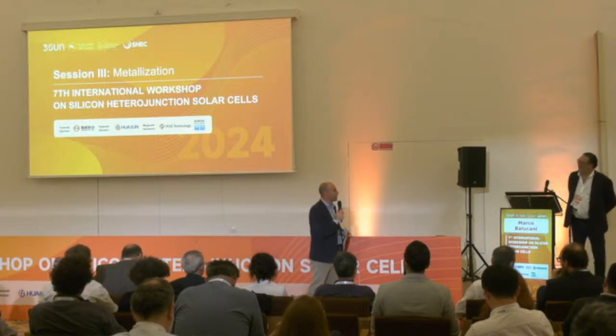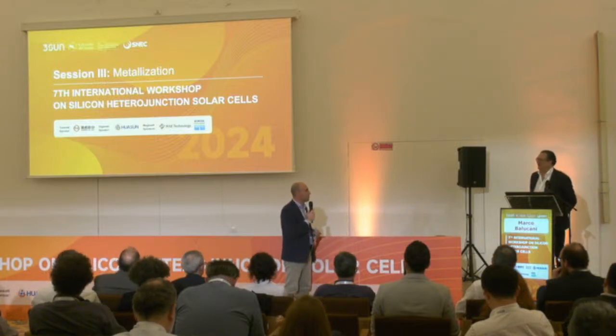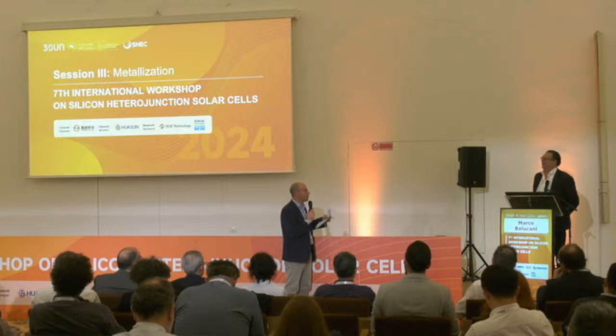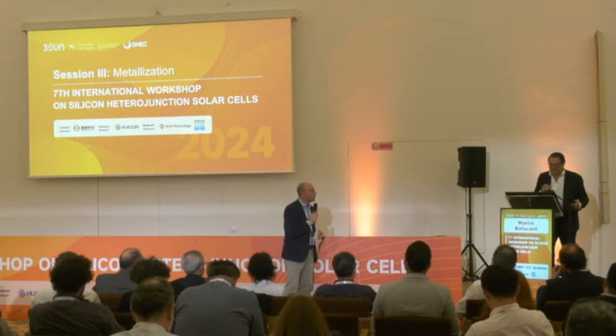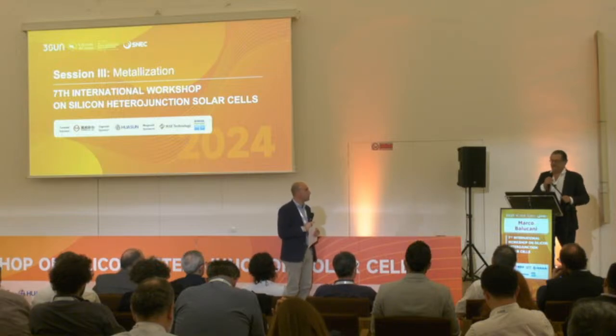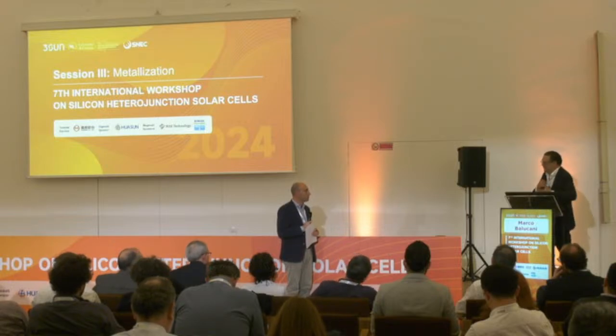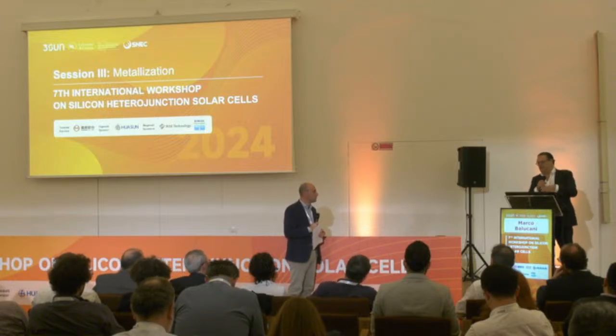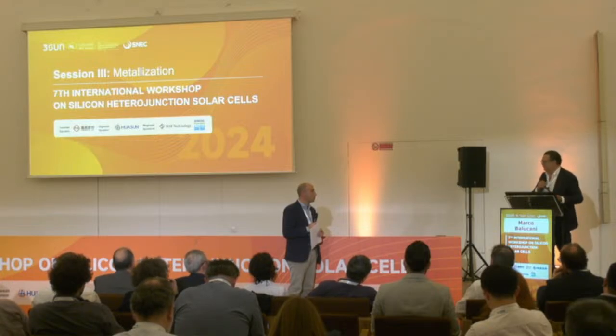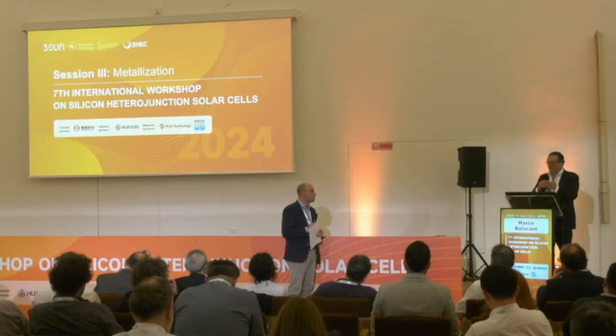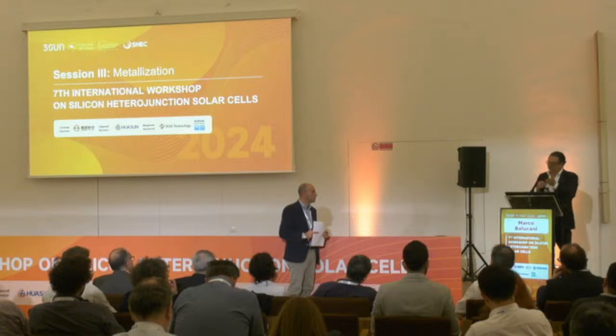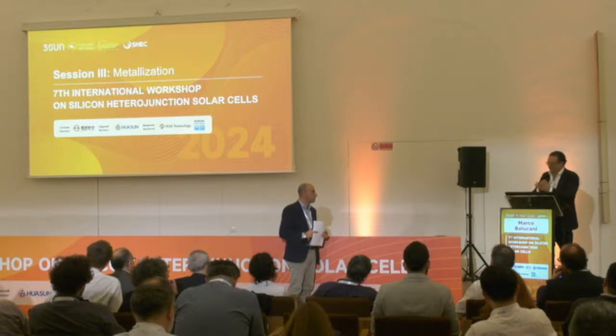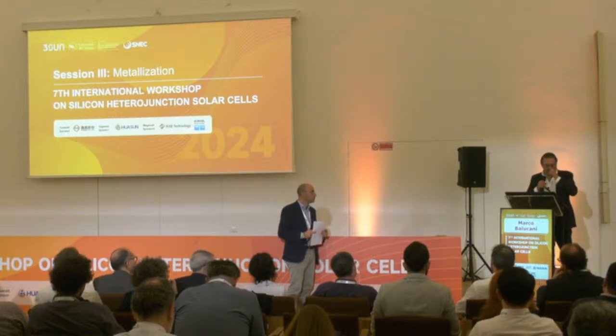Can you comment on finishing your copper fingers for future soldering? This technique allows you to put any kind of metal with this localized technique, so it can even be silver if you want. If you want to use ECA, we can put 50 nanometers of silver to cover and give the contact, because silver paste directly on copper I would never put, as you can have corrosion due to the presence of the paste.